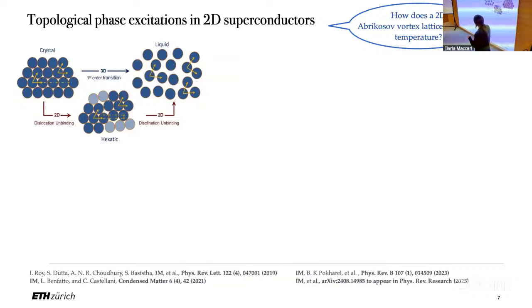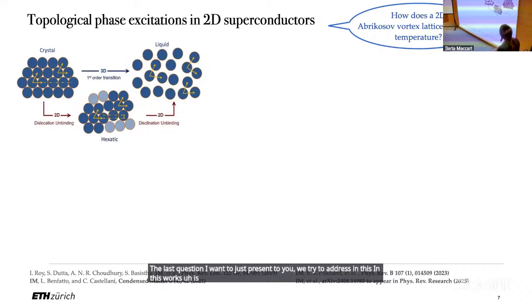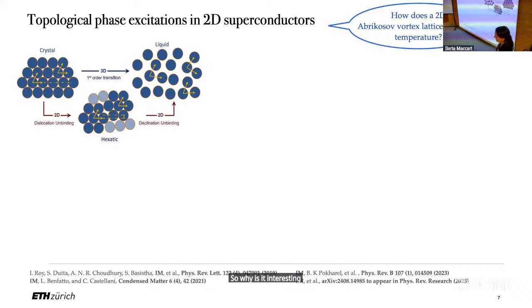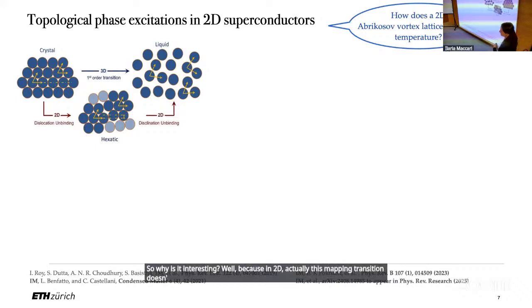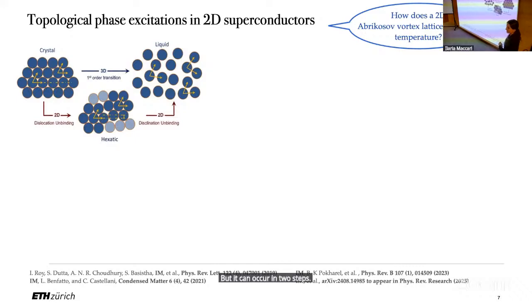The last question I want to just present to you, we try to address in these works, is about the melting of the two-dimensional Abrikosov vortex lattice that forms in thin superconducting films when you apply a perpendicular magnetic field. So why is it interesting? Well, because in 2D this melting transition doesn't occur like in 3 dimensions, so via just one single step from a crystal to a liquid phase, but it can occur in 2 steps via an intermediate phase, which is called the vortex hexatic liquid phase.